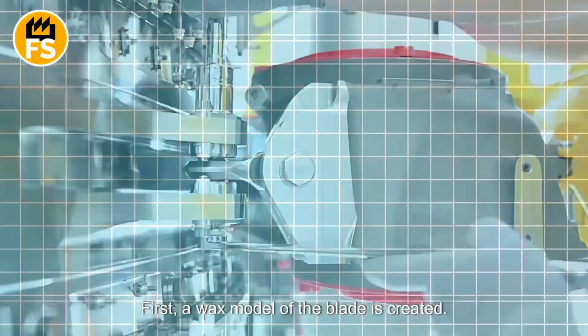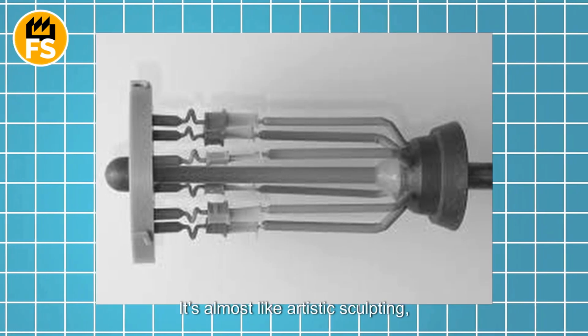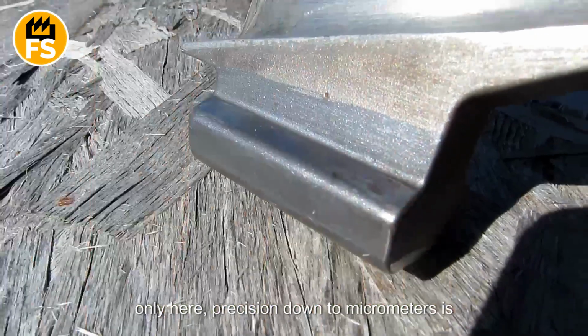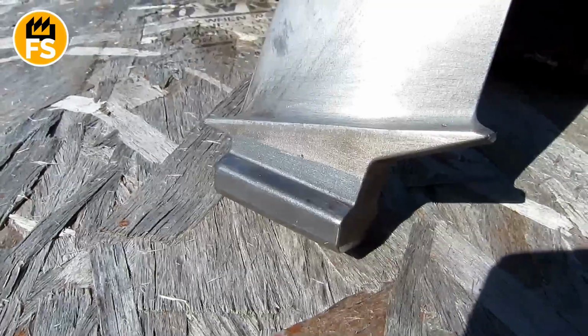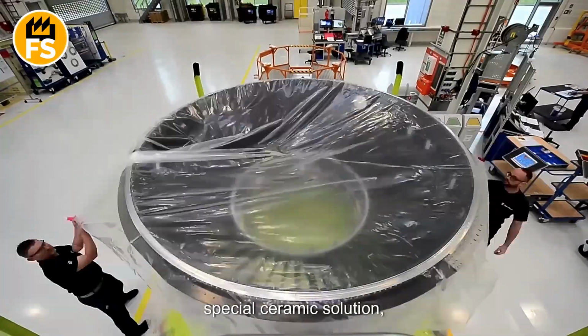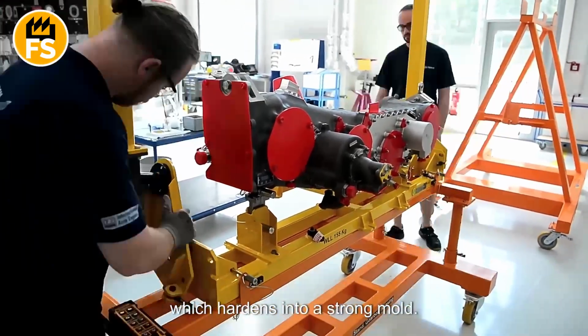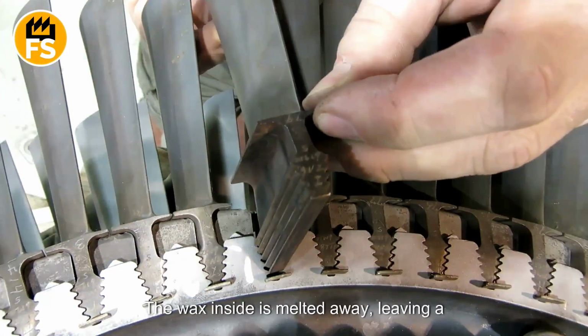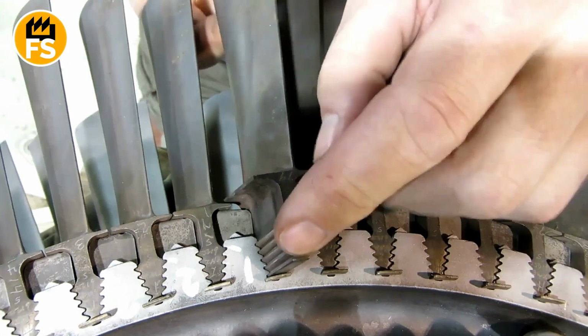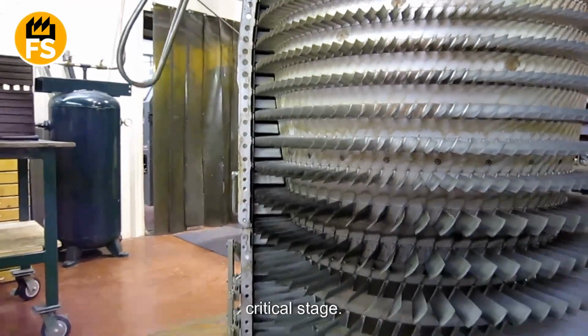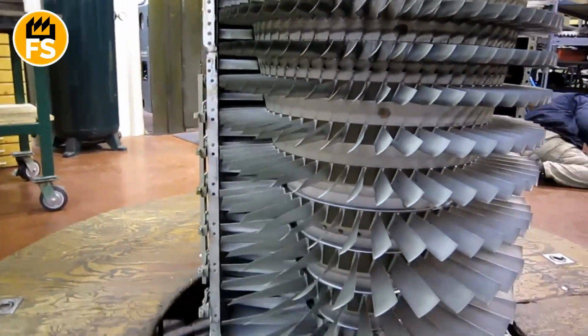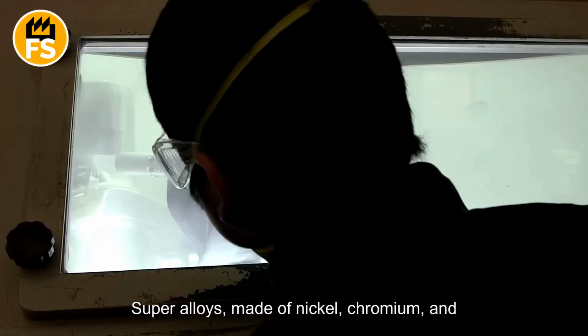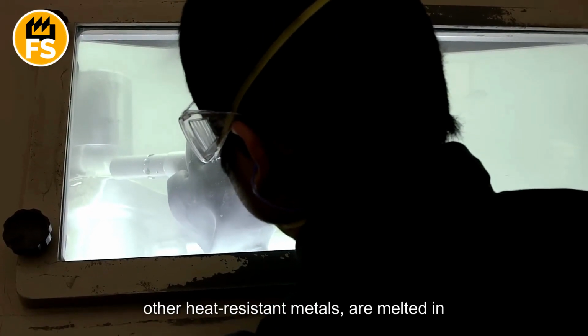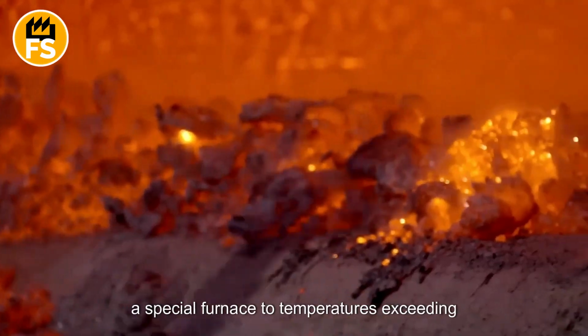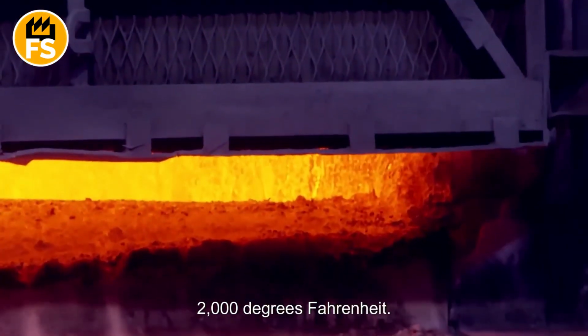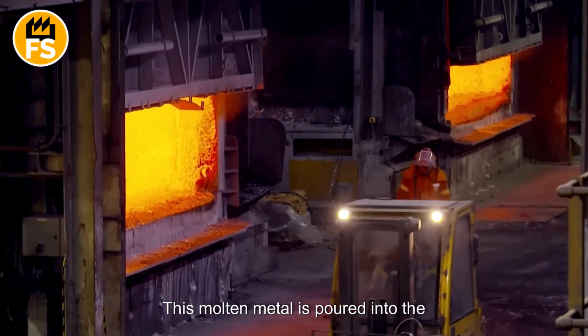First, a wax model of the blade is created. It's almost like artistic sculpting. Only here, precision down to micrometers is crucial. This wax model is then dipped into a special ceramic solution, which hardens into a strong mold. The wax inside is melted away, leaving a perfect cast for the blade. The ceramic mold is now ready for the most critical stage. Now comes the real show. Superalloys, made of nickel, chromium, and other heat-resistant metals, are melted in a special furnace to temperatures exceeding 2,000 degrees Fahrenheit. This molten metal is poured into the ceramic mold.